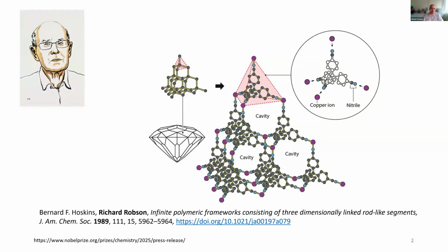Richard Robson, in the late 20th century, discovered that when playing with structural models such as diamond, which is depicted here as a classical diamondoid net, substitution of individual carbon atoms in that diamond lattice by tetrahedral molecules, such as these ligands depicted on the top right, could result in the formation of isostructural framework materials that bear the same sort of structural topology as the diamond net, but due to the larger size of the molecular building blocks, results in a vast expansion of this isoreticular net under the production of cavities inside this framework.